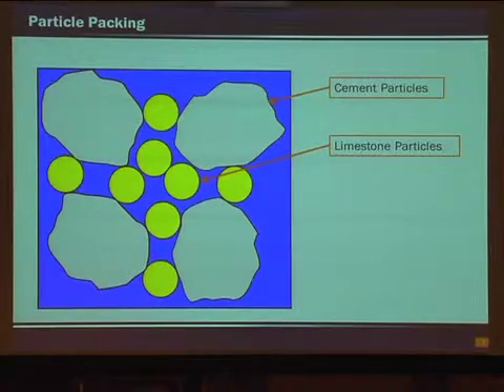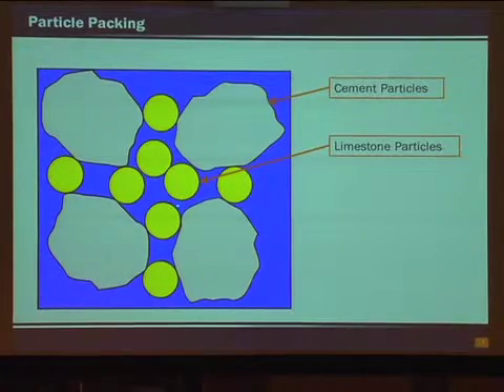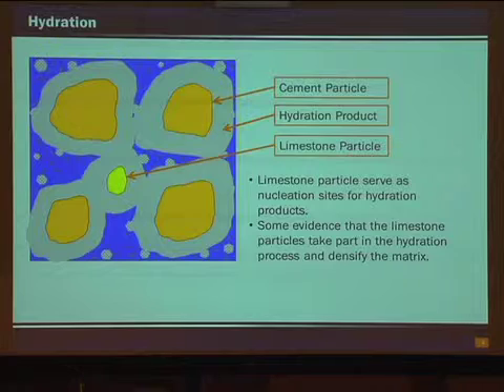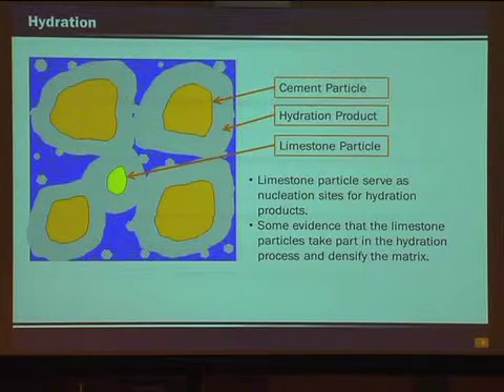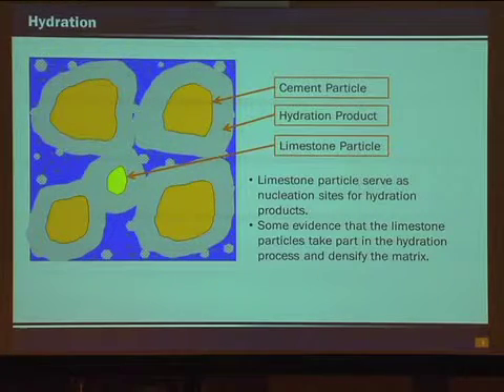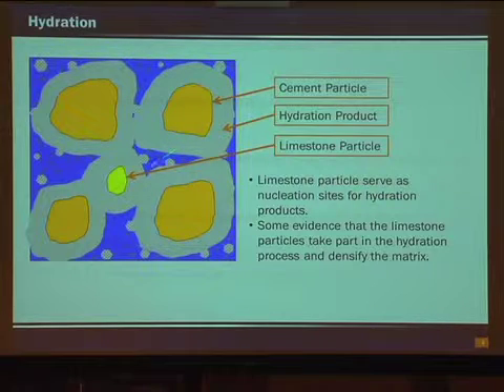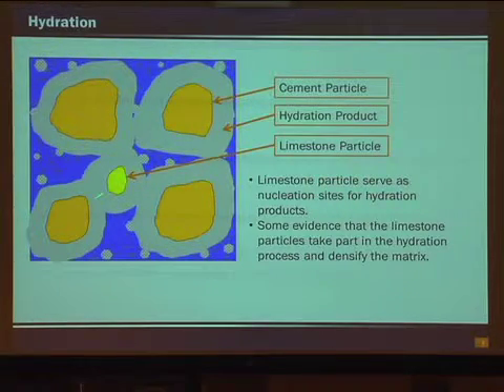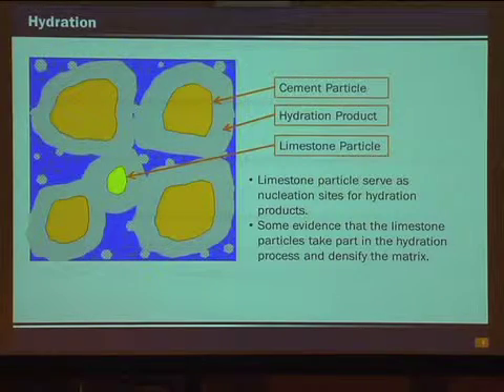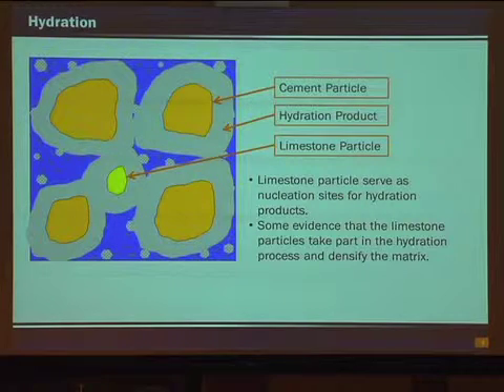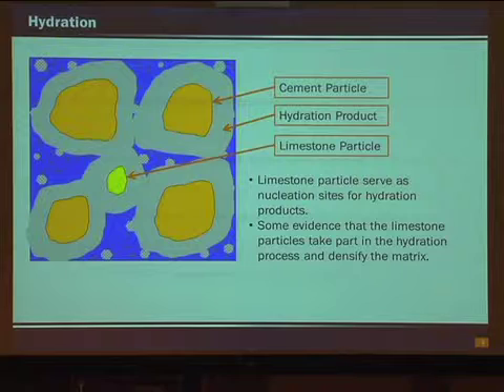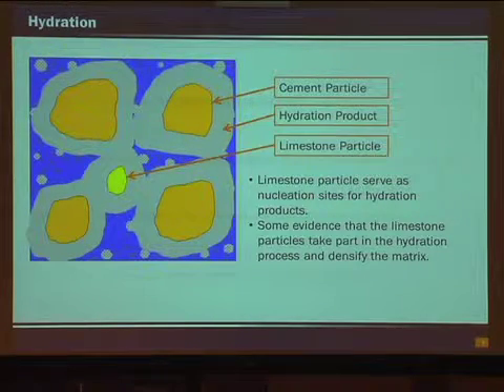So what happens at that point? Well, you have cement grains, and then you have limestone particles. The limestone particles being finer will pack in between the cement grains, causing less bleed and giving you a little more strength, because now you have less space for hydration products to grow, which is indicated here. You have a limestone particle. Limestone particles tend to act as nucleation sites, basically a place where hydration products like to grow. They start growing on the limestone particle and the cement grain. There's less distance for those hydration products to grow and meet up in the middle. So you get the strength benefit by having this space reduced because of those limestone particles being interdispersed between those cement grains.